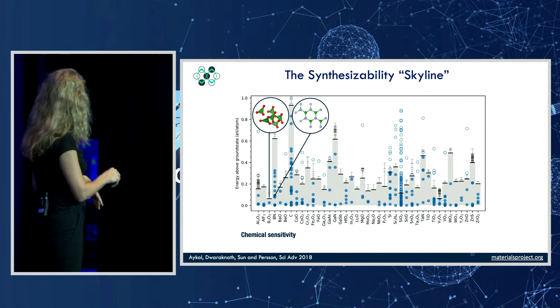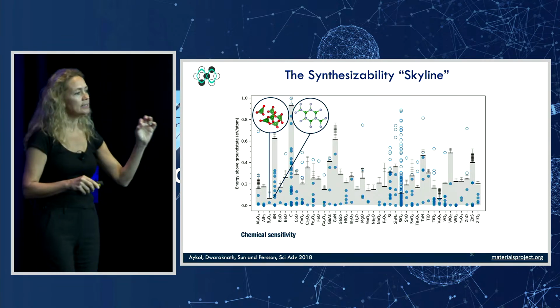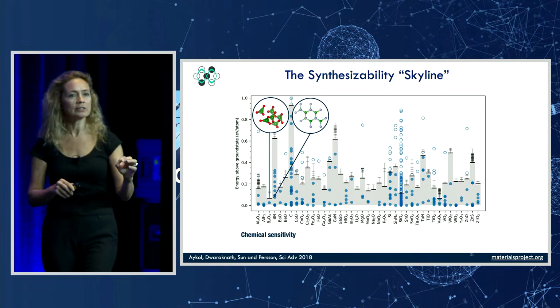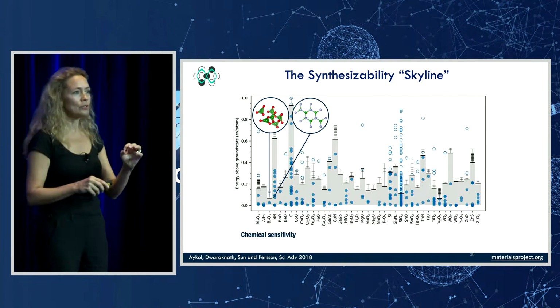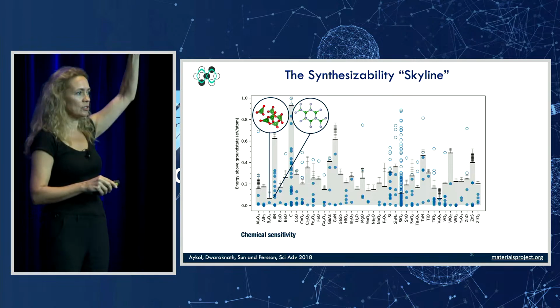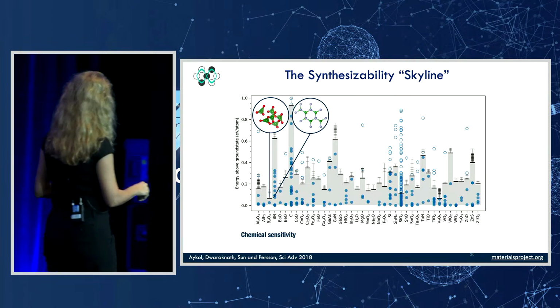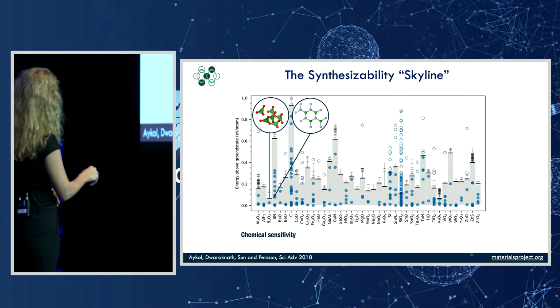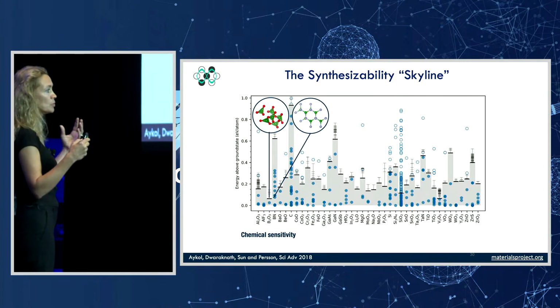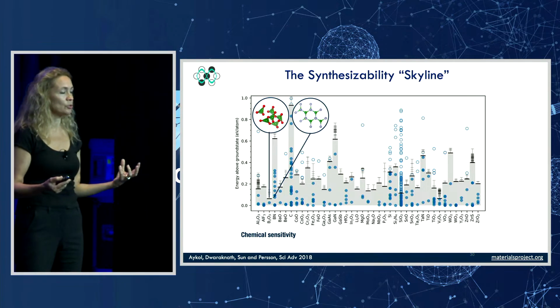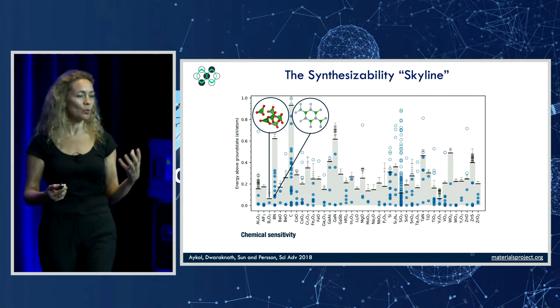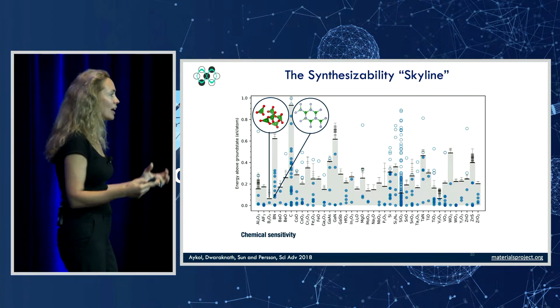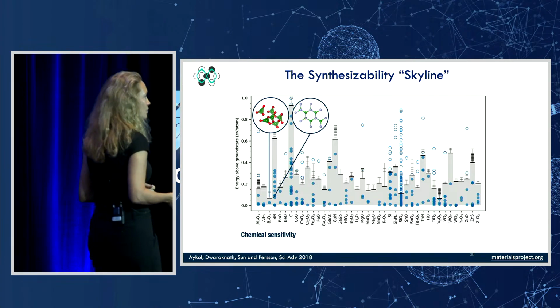But if you take boron nitride, which has these highly directional covalent bonds, then you're going to deal with a much higher amorphous energy because it hates being amorphous. So very high enthalpy of formation. And that means, in turn, that you have a much larger window of opportunity for metastable materials to form, which is great, right? That's what we like. We like to have some playground in order to make these different kinds of structures.